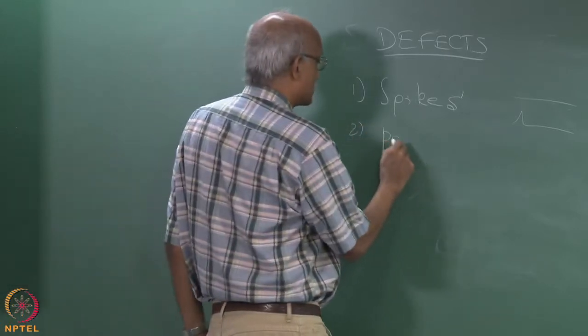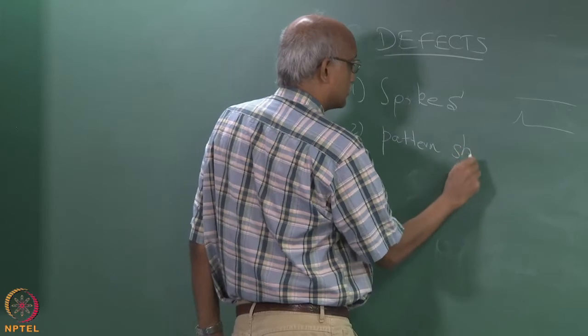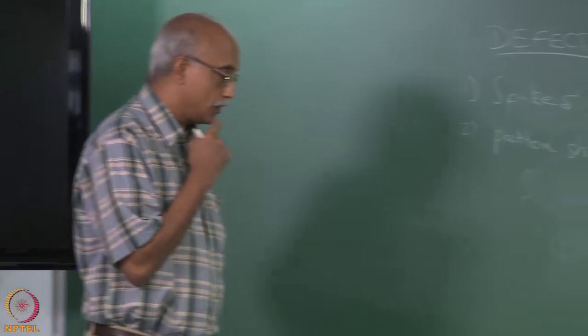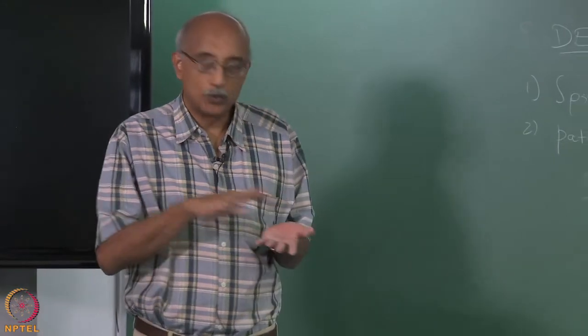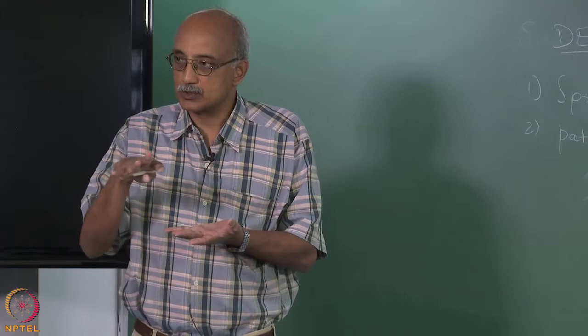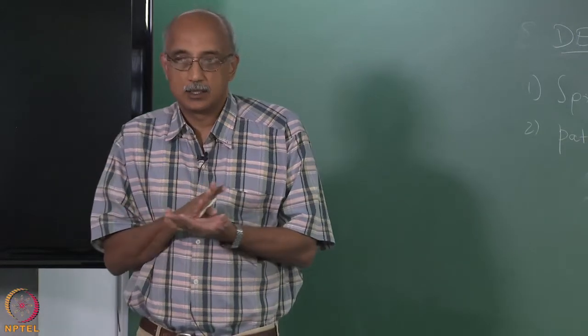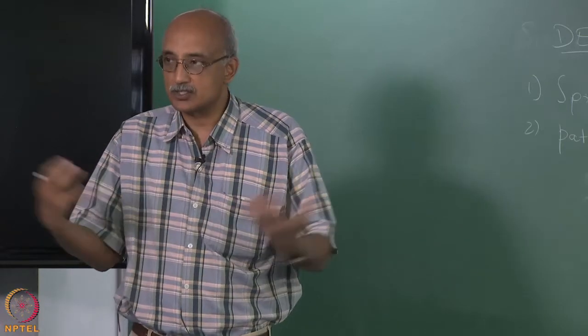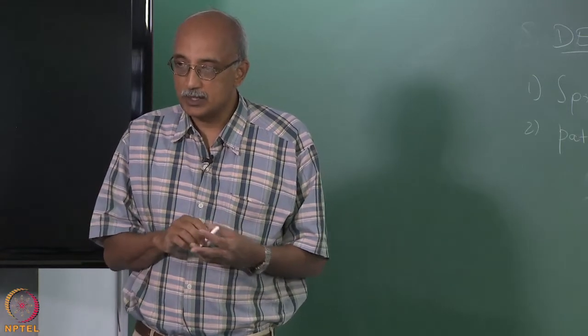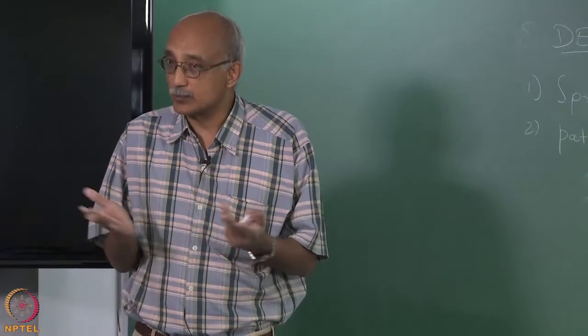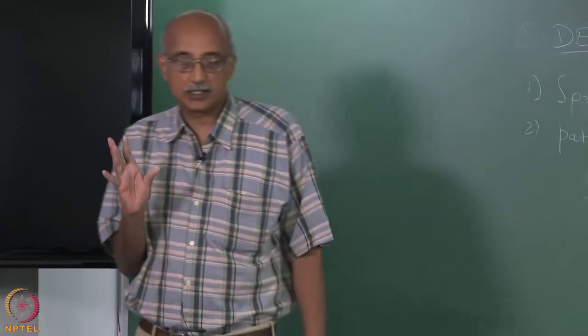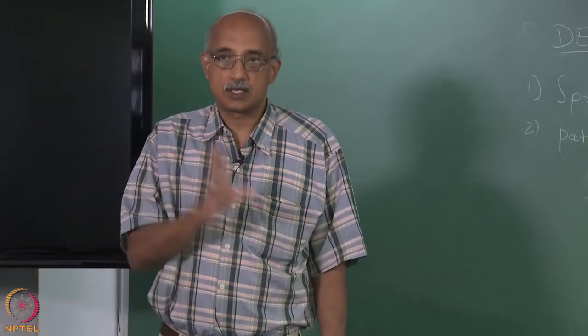The second type of defect is known as pattern shift. A pattern shift happens when the crystallinity itself is affected. For example, if your growth rate is too high, if your deposition rate is too large, then instead of growing in a single plane like it's supposed to, you may start growing a plane at a different angle just to accommodate the extra material that's coming in, or you might actually add another plane to your film which is not supposed to be there. So these types of defects essentially lead to a change in the crystalline pattern of the film itself.